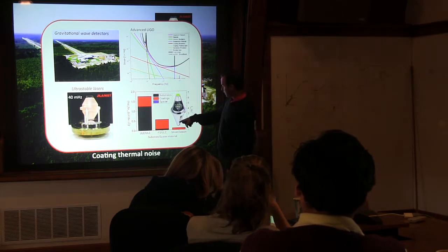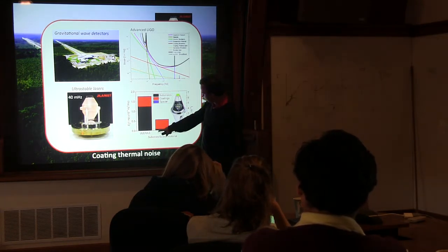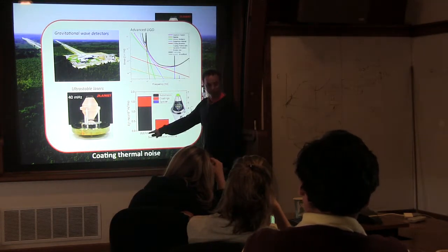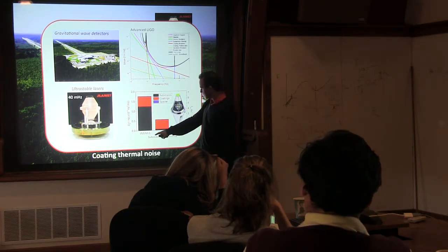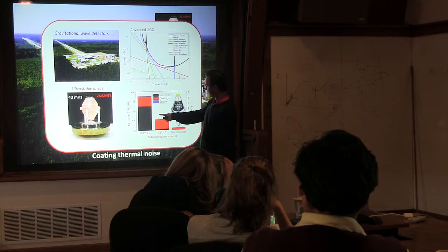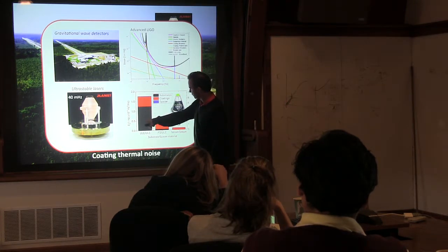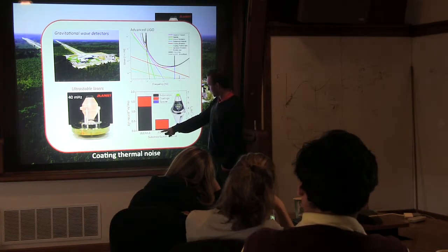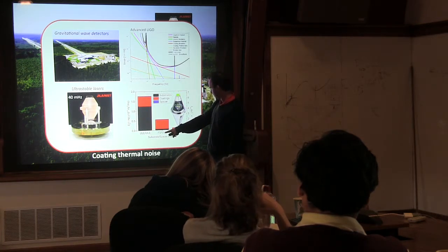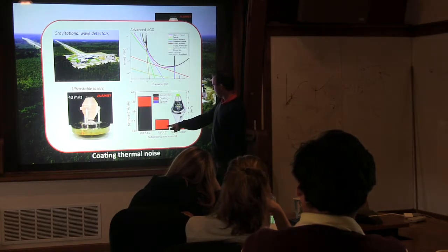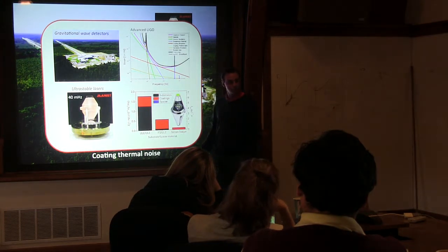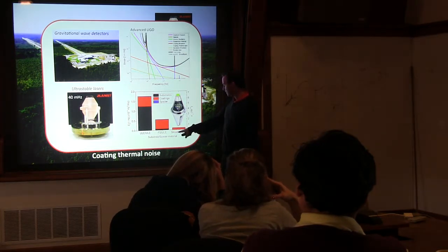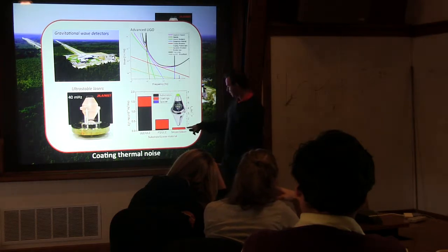Okay? And so basically, here's a study of the different combinations. So the ULE spacer and ULE substrate. You see in that case, this ultra-low expansion material has extremely bad mechanical quality compared to other systems, so that the noise is dominated by the substrate. If you go to fused silica for the substrate, and ULE for the spacer, you see that you kill the two contributions from substrate and spacer, and you're limited by the coating. And eventually, if you go to the silicon-silicon cavity, which is the one that has been built, there's only the coating contribution.